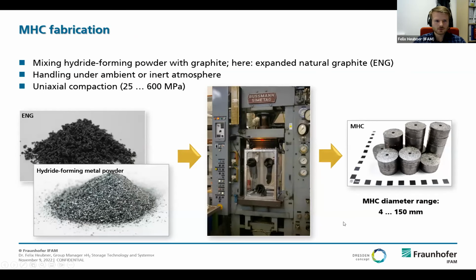These composite materials are made in uniaxial presses that are known in the powder metallurgy industry for several years. They were used in the past for producing gear parts, for example. It's one very famous example. So this machinery can be used for producing composite materials for hydrogen storage here as well.